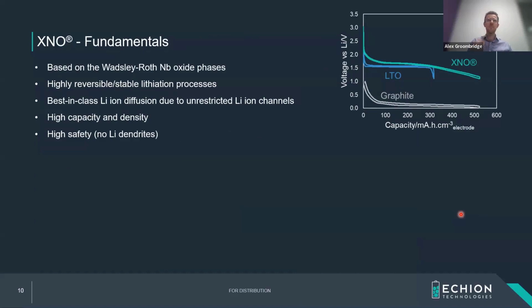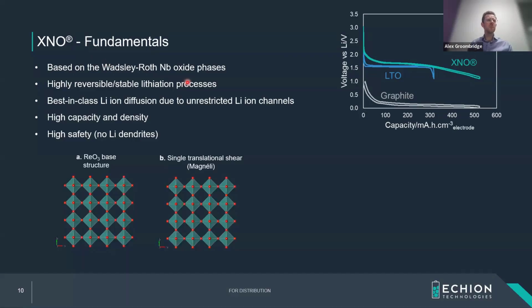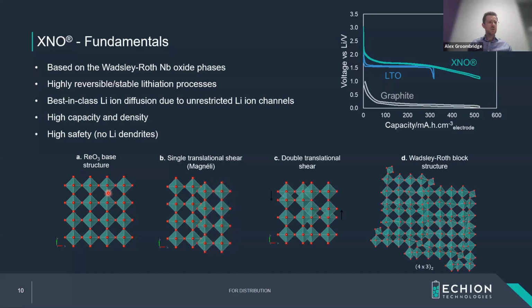So how does it work? So XNO, niobium based, these are based on the Wadsley niobium oxide phases. So what this means is its crystal structure, the arrangement of the atoms in space. I've got a schematic down below to explain what these Wadsley niobium oxide phases look like. We have structures here of niobium surrounded by oxygen atoms, and there will be other elements in there as well. And in order to get these structures, rather than a perfect octahedral matrix, as you have on my diagram on the left, these crystal structures are formed by having some shear effects taking place. You end up with oxygen sharing.